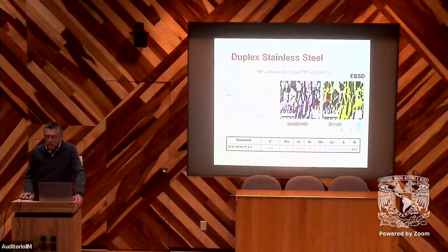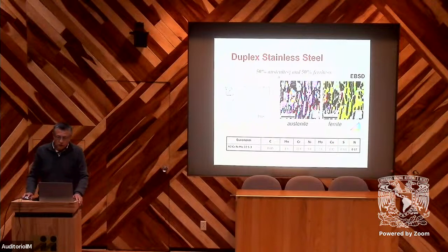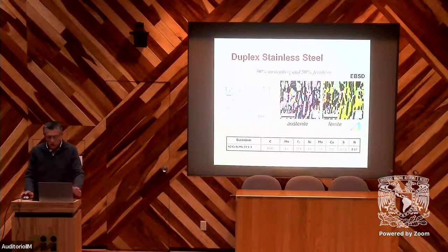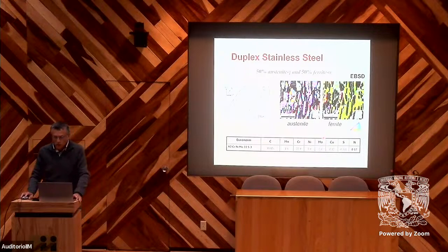So we use neutron diffraction to study the stainless steel, with 50% austenite and 50% ferrite. This is obtained by the balance between gamma-gen elements and alpha-gen elements. We have here the equilibrium between chromium and molybdenum, and manganese and nickel.